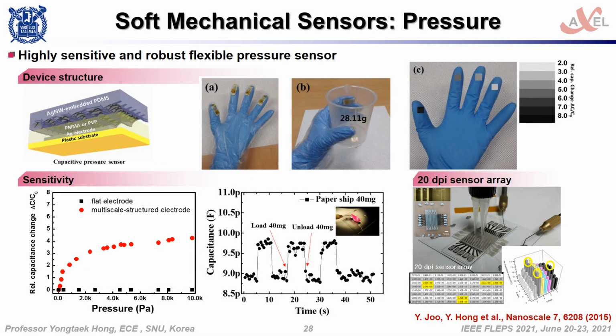This slide shows a pressure sensor and 20 dpi sensor array developed by my group. Hierarchical structure of silver nanowire electrode features high sensitivity. Pre-stretching and spray printing method was used for the top electrode of the capacitive pressure sensor device.